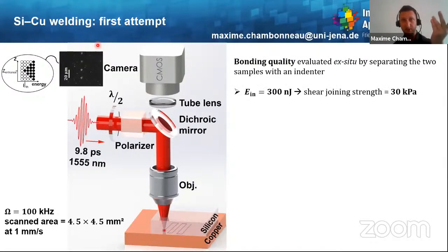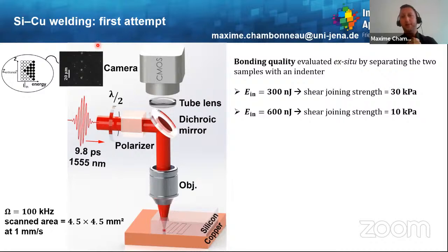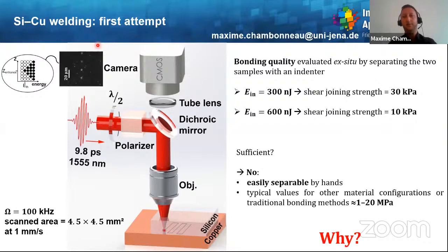If we set the input pulse energy to 300 nanojoules, then we are able to measure a shear joining strength of around 30 kilopascal. Okay, good to know. Then what if we double the energy, like go to 600 nanojoules? Then the shear joining strength is lower, it's 10 kilopascal. So this behavior is quite surprising, but the main question is: is that sufficient for envisioning some industrial applications? And sadly, the answer is no, as in that case, the samples are easily separable by hand.